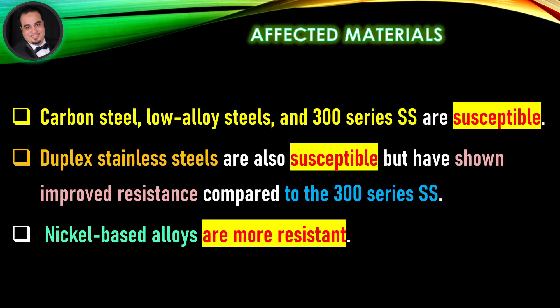Affected materials: Carbon steel, low alloy steels, and 300 series stainless steel are susceptible. Duplex stainless steels are also susceptible but have shown improved resistance compared to 300 series stainless steel. Nickel-based alloys are more resistant.